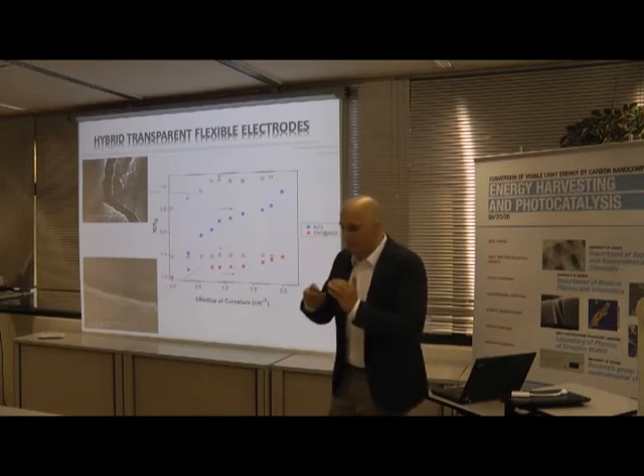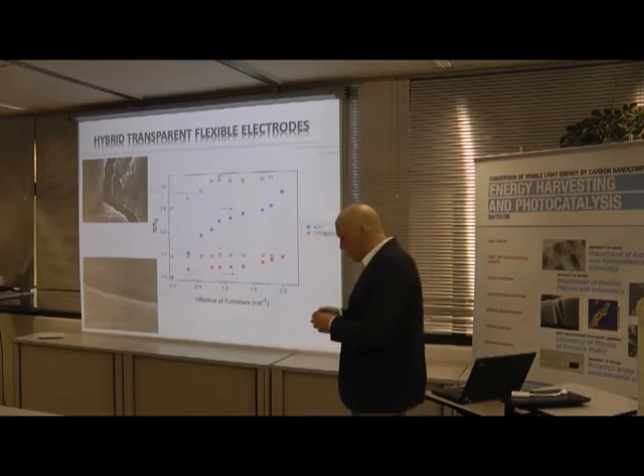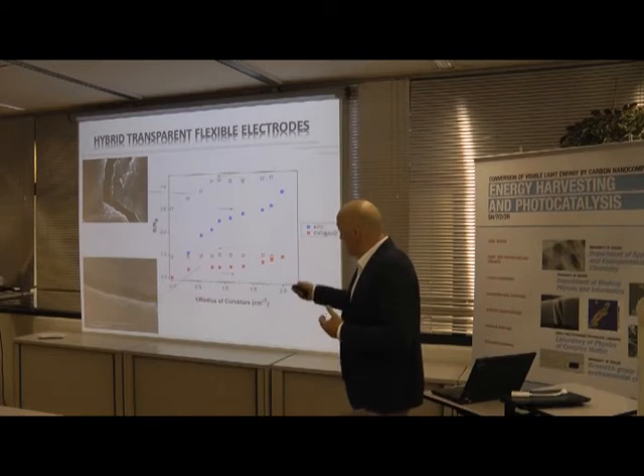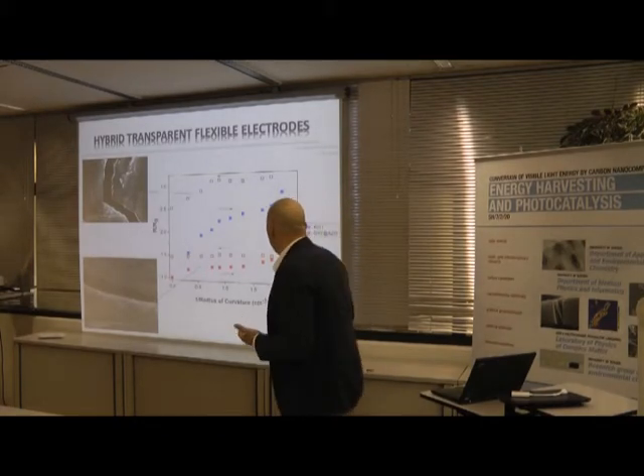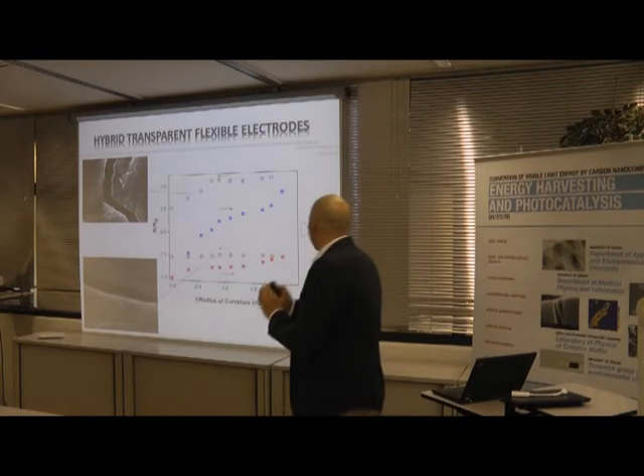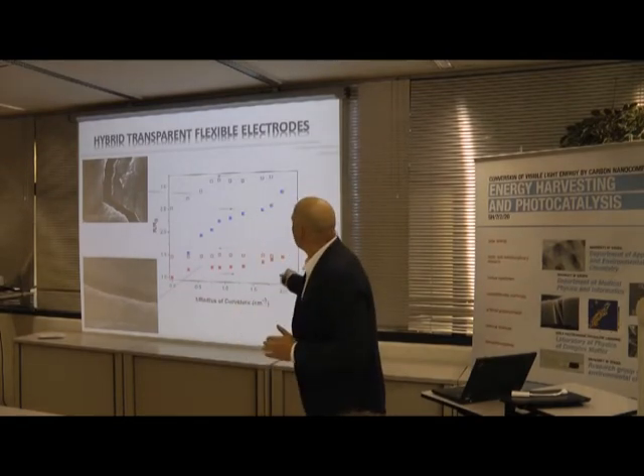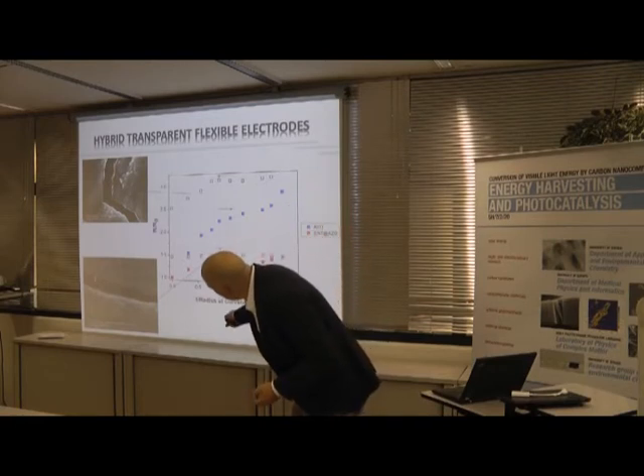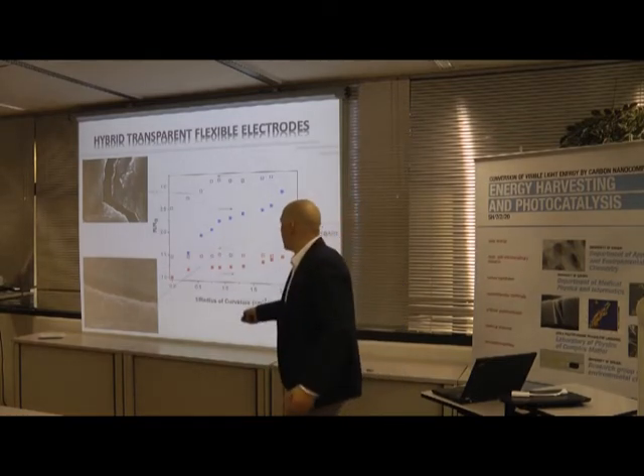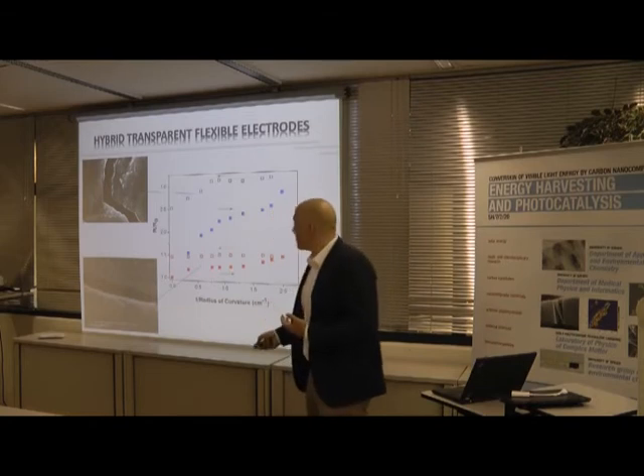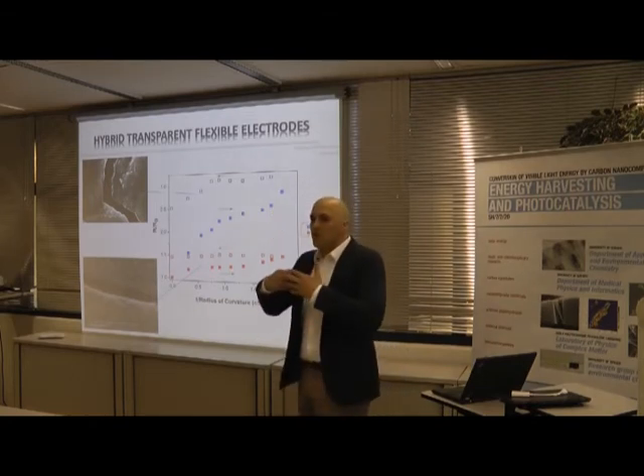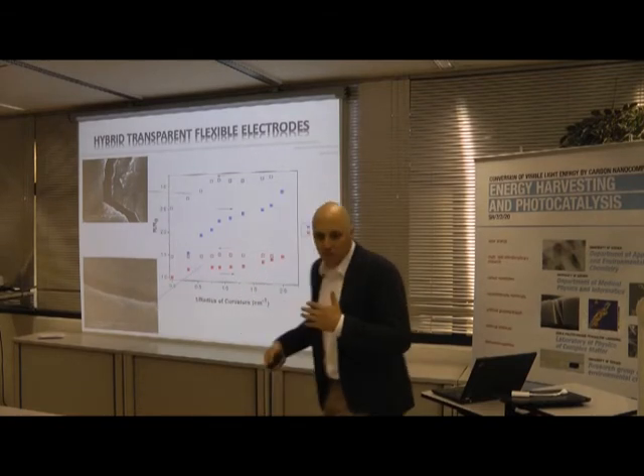And we tested the fatigue. It turned out that, of course, if you deposit a rigid brittle ceramic on the surface of the plastic, when you bend it, you see the grain boundaries or the cracks. And this material, if you bend it with a radius of curvature of 2 millimeters, quickly lost conductivity. But the other sample here, I don't know if you can see, the carbon nanotube composite, the hybrid thin film, had much better resistance. This is because the carbon nanotubes were stabilizing the crystals and bridging the gaps which were opening. So when you go back, you recover some conductivity.